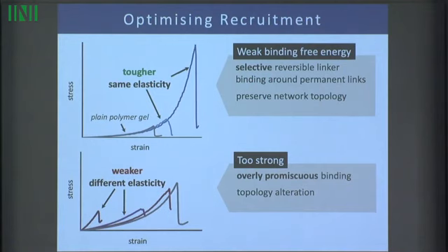So I touched upon this, but how do we optimize this recruitment effect? It's really about the binding free energy. And so we want to design reversible crosslinks that can pay the cost for binding just near a permanent crosslink, but not farther away. Okay? That will give us this weak binding free energy regime, and that will hopefully lead to the topology of the network being maintained, and then we end up with this interesting stress strain behavior where we enhance the toughness of it.